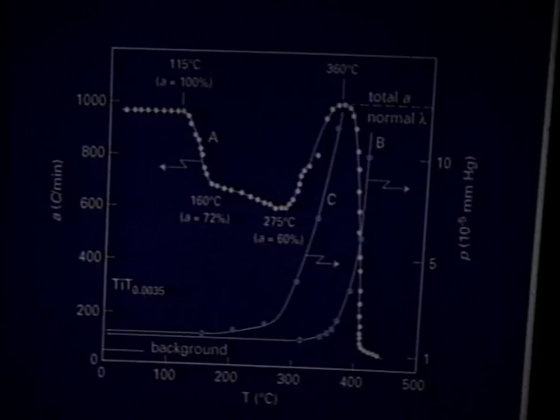In the temperature region between 150 degrees centigrade and 275 degrees centigrade, a new tritium compound, I call it preliminarily a compound, is formed in our preparation with a lower radioactive decay constant, and upon further increase of temperature and before decomposition of the preparation, this lower emitting compound is destroyed.